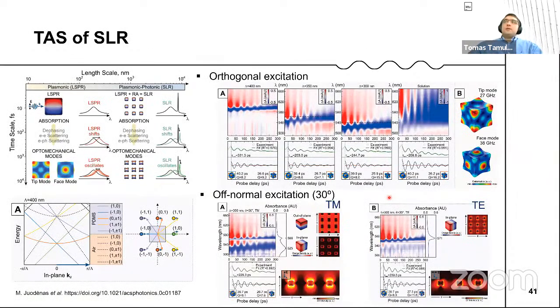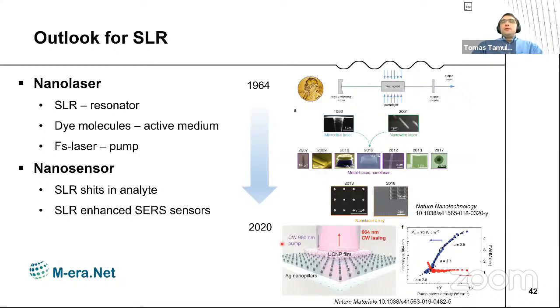And what we also observed is that you can expect that if a nanoparticle is oscillating, so you are changing the plasmon resonance condition, this SLR, which is related to this plasmon resonance, should also shift. And we observed that it's really shifting as well. So that was a very nice work by Mindaugas. He just defended his thesis recently, where we showed that we can follow this SLR in transient absorption spectroscopy. So we can manipulate this very narrow line in time, and we see that there are some nice applications for that in the future. So there's some outlook for these SLRs.